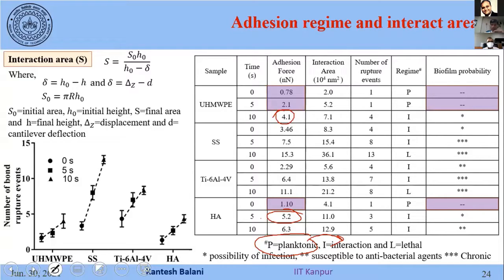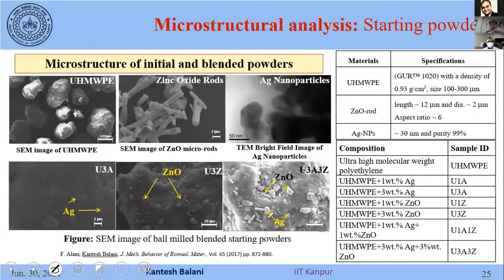Whereas stainless steel or titanium, I think they have very strong interaction with bacteria, and they can directly be in the lethal regime, and they have very high chances of infection. So it can become a little bit of a problem. I just want to highlight this finding has proved the convention wrong, that hydroxyapatite was supposed to be taken as a biomaterial for antibacterial property, but that is not so. This was very nice, I think, this belief which was proven wrong.